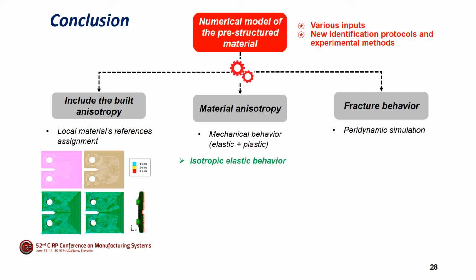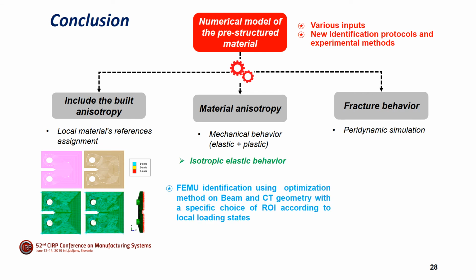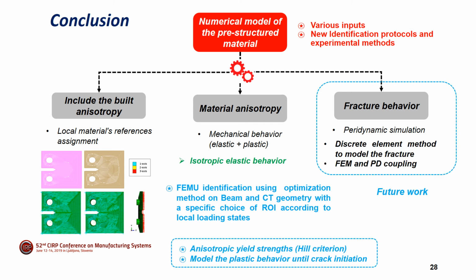What we have developed for the cost function evaluation can obviously be used to re-identify all four elastic constants at once via a finite element model updating identification with an optimization method on beam or CT geometry, with a specific choice of region of interest according to local loading states. Work in progress concerns identifying an anisotropic yield criterion, which is the Hill criterion, and the plastic model that goes into crack initiation. Then, the next step will be to model fracture using peridynamics simulation.